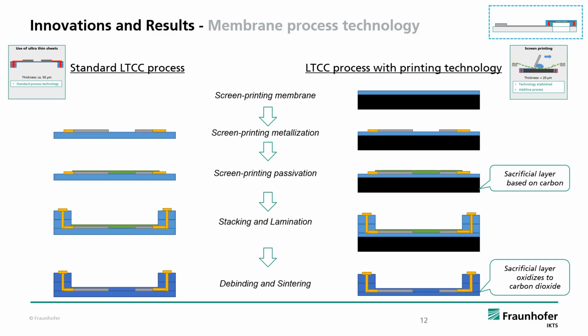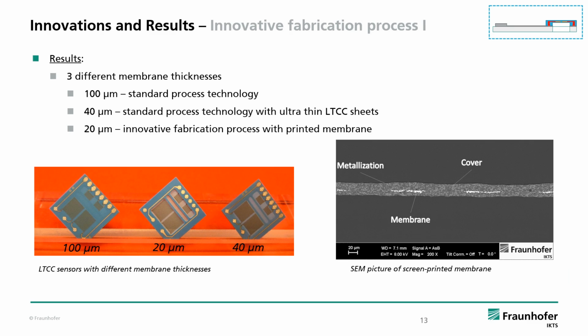So on this slide I want to compare the results of the innovative fabrication process 1 with the standard technology. We prepared sensors with different membrane thicknesses. One has a 100 micron thick membrane prepared with the standard LTCC process, analog to the standard process with the ultra-thin LTCC sheets, which results in a 40 micron membrane. The new technology with screen printing, the membrane, instead of using LTCC green sheets, results in a 20 micron membrane.